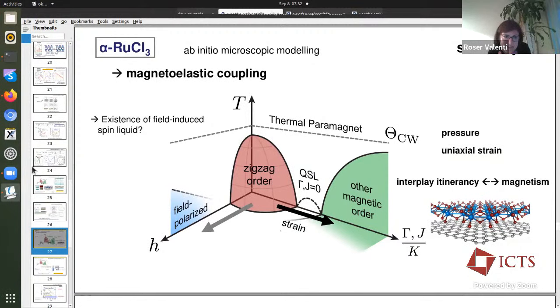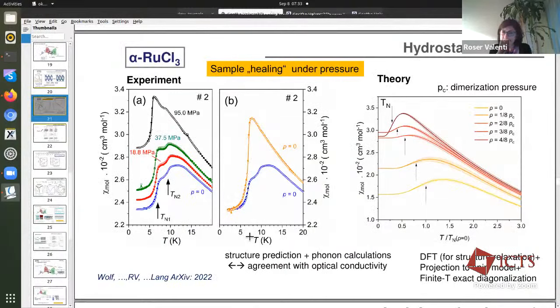Yes. Thank you, Harald. This is why I was presenting this one slide from Michael Lang. The point is that one should do X-ray, for instance, at low temperatures, because the structure at low temperatures is not well defined. In this material, there are two structures that one is mostly discussing. One is the C2/m structure, and the other one is in fact a rhombohedral structure. The difference between the two is that in the C2/m structure the stacking is like that.